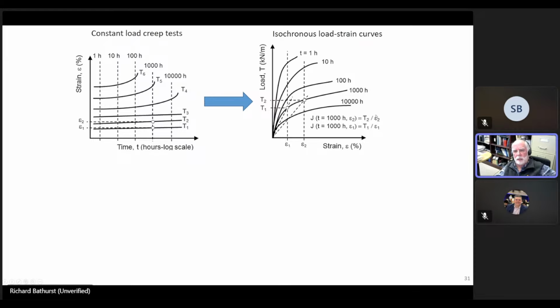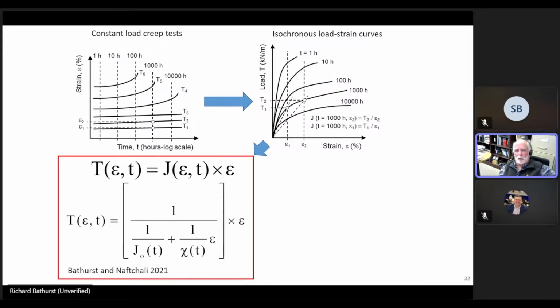strain at different times. And here I just want to emphasize again that a constant rate of strain test at 10% strain per minute does not have the same appearance as these isochronous load strain curves taken from constant load creep tests. From these isochronous load strain curves, we can fit a hyperbolic model that captures the nonlinear trend that you see in these plots, and can be used to develop a stiffness model.